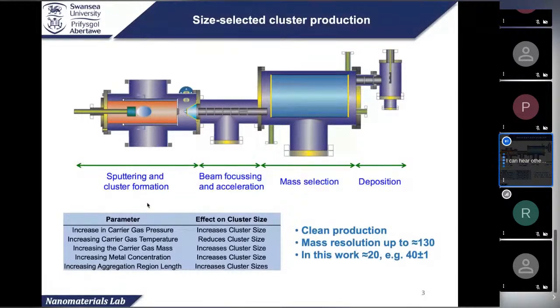You can tune the size of the cluster by tuning the gas flow, like argon and helium, in the first chamber, and then you can change the sputtering power, and basically you change the amount of atoms in the generation chamber. Then you change the aggregation process. Then you just tune the isomers to different sizes.